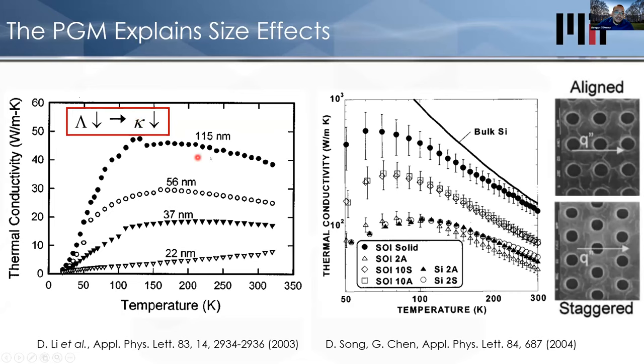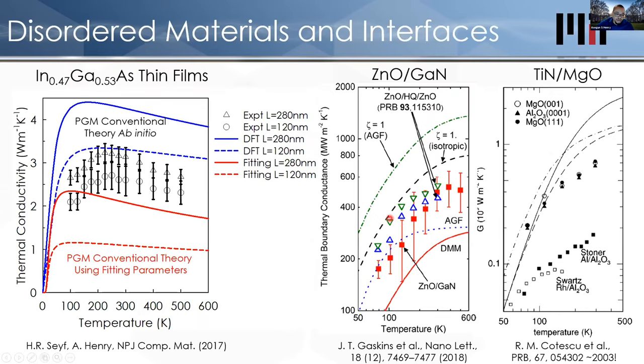So this here is the thermal conductivity of some silicon nanowires. As you shrink them, the thermal conductivity decreases. You can see that if you drill holes in a piece of silicon, the thermal conductivity starts to decrease, because now the distance that phonons can travel before they run into the edge of a hole is getting smaller. And so this phonon gas model makes sense of all of this. It's a great model for that.